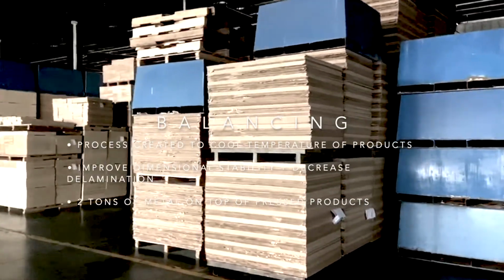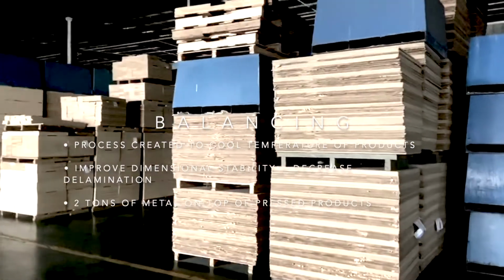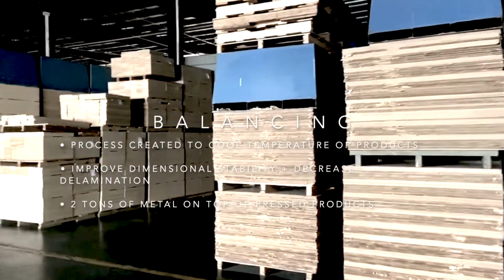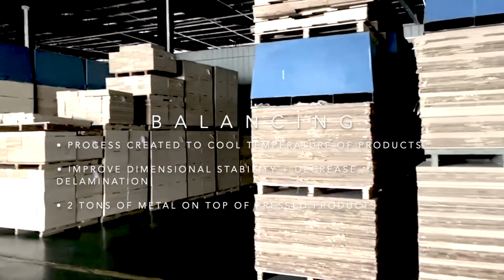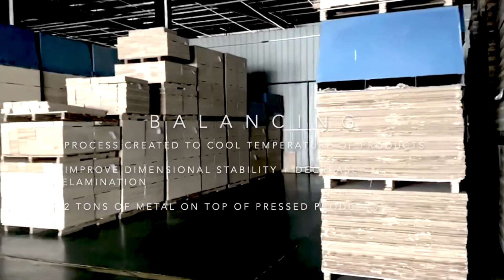Phase 6, balancing. This is a process where 2 tons of pressure are placed on the product for about 10 days. Reason for this is to help aid cool down, improve dimensional stability, and decrease delamination possibility down the road.